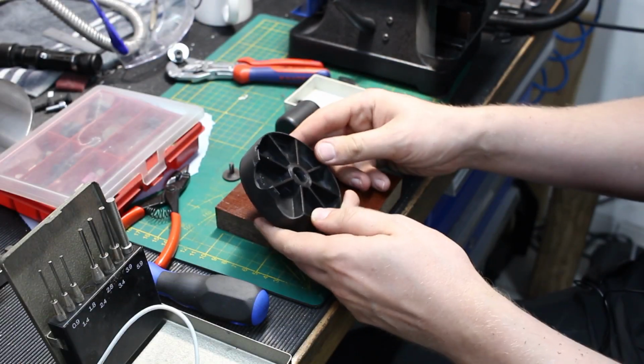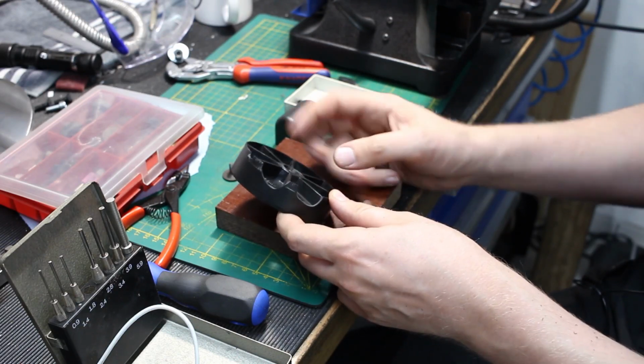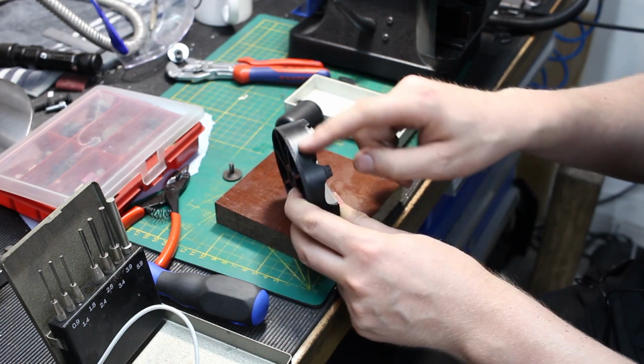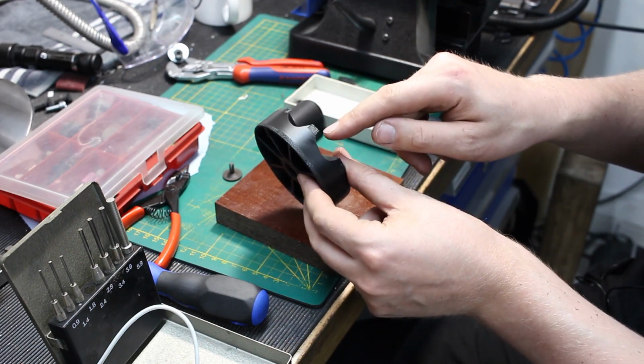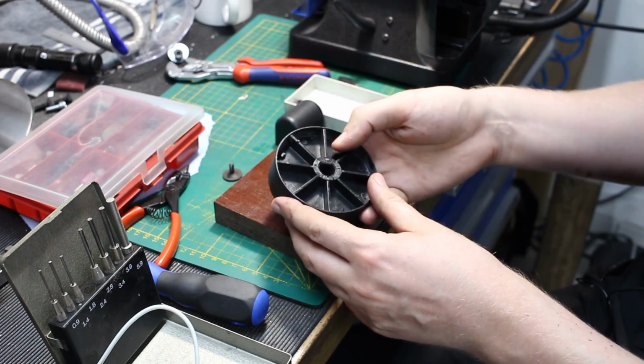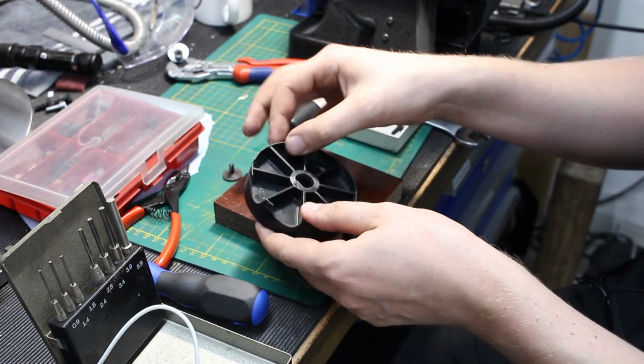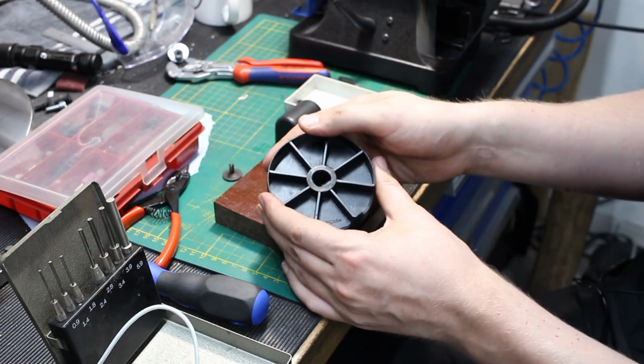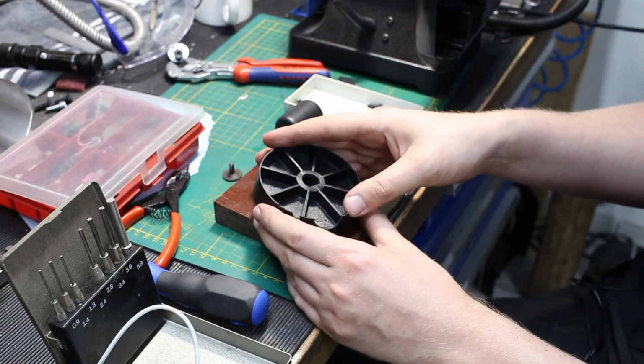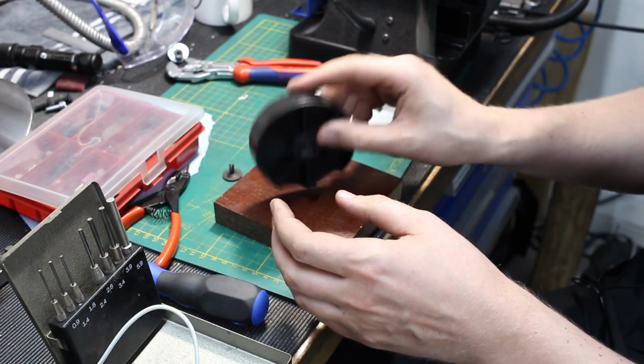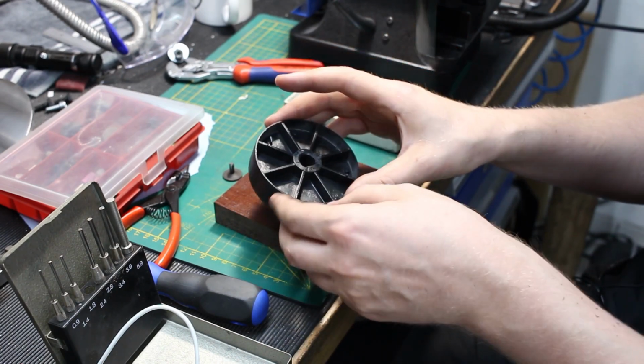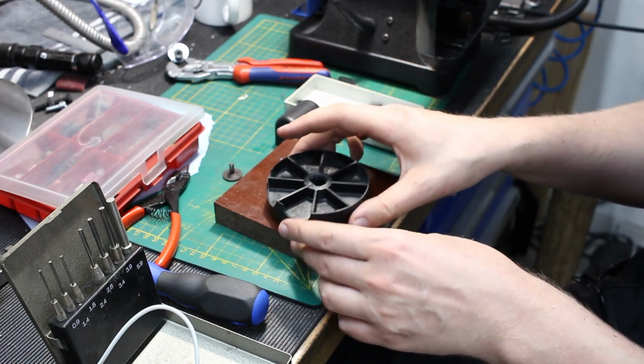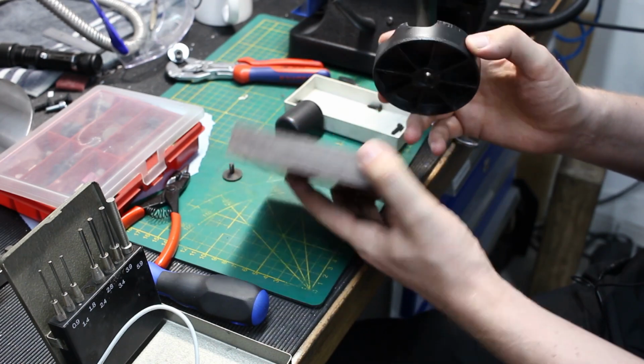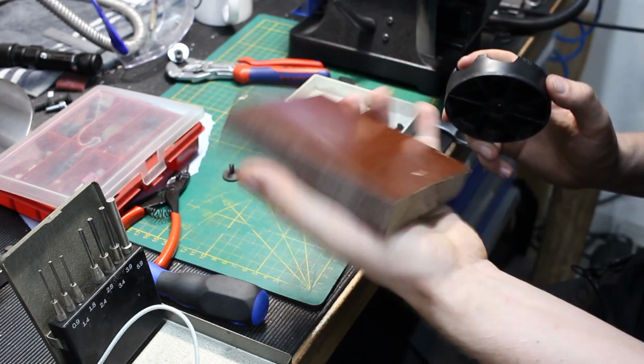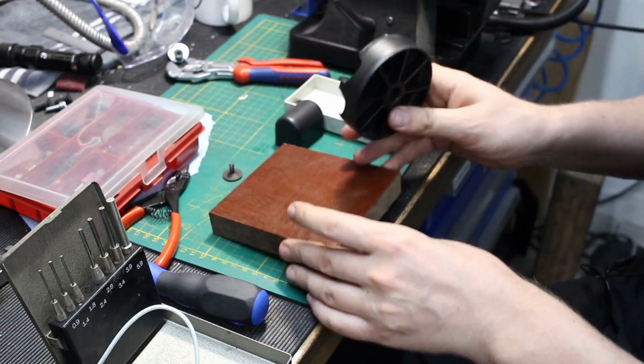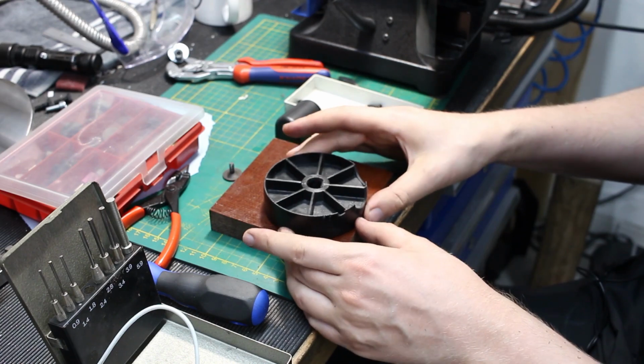Okay, I destroyed the original drive wheel. I put it in a lathe on a mandrel, and I turned the OD through, and at some point it catched and it destroyed itself. Which was a little bit expected because it's all very thin and the Delrin they used is crazy brittle. I don't know Delrin to be that brittle. Sounds almost like a blend with a different plastic. I'm not sure. So I found a piece of phenolic, linen reinforced phenolic, which is quite heavy. The right thickness and the right size, so I'm going to make a new wheel.